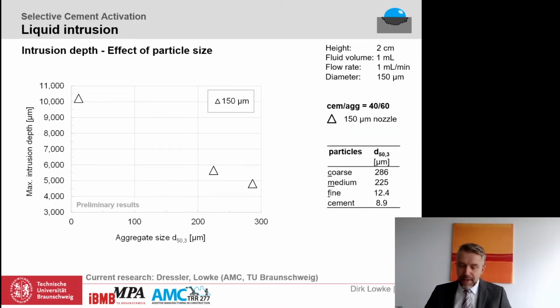Okay, if you now plot these results as a function of particle diameter, we see a clear trend that the penetration depth decreases with increasing particle size. At the same time, however, the ratio of width to depth increases too, which indicates that the water is increasingly distributed horizontally as the particle size increases.